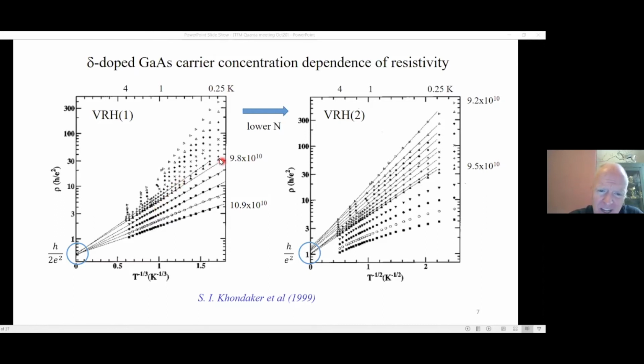Then at lower carrier densities, changing the carrier density with a gate, the system doesn't behave as if it's Mott. It switches over to Efros-Shklovskii. If we replot the same data versus 1 over T to the half, then at the lower temperatures we have this activated behavior according to Efros-Shklovskii. At lower temperatures, this larger hopping distance comes in with the extra term. You can see clearly the high temperature intercepts: h over e squared for Efros-Shklovskii, h over 2e squared for Mott. Very interesting.